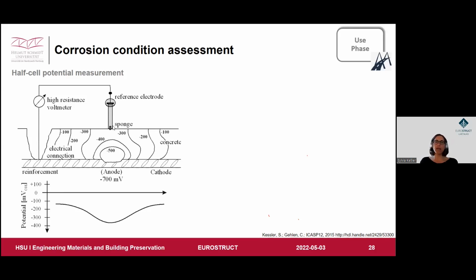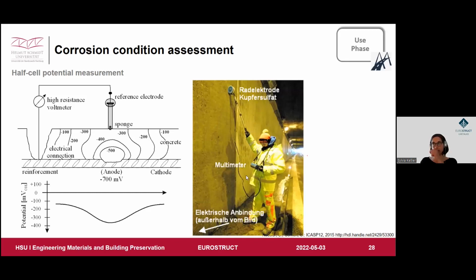If we now scan the whole concrete surface, not only with a rod electrode, as you see here, but with a wheel electrode as you see in the picture, you can easily scan huge surfaces in order to get the information about the half cell potential. And this is the only slide where I bother you with some German. These are now the equipotential plots. It's normally the representation of any half cell potential measurement.